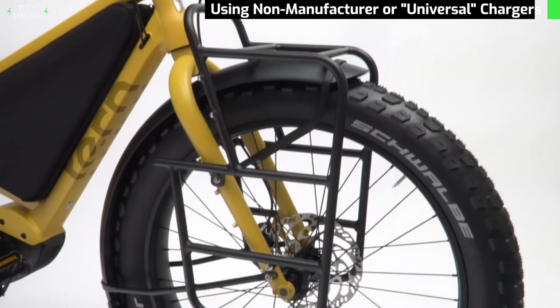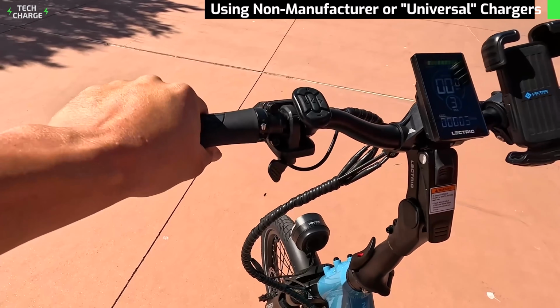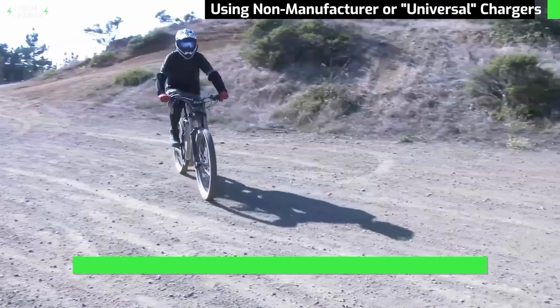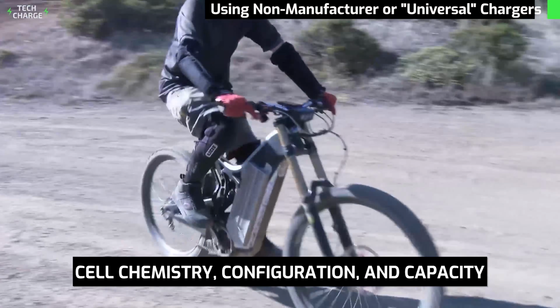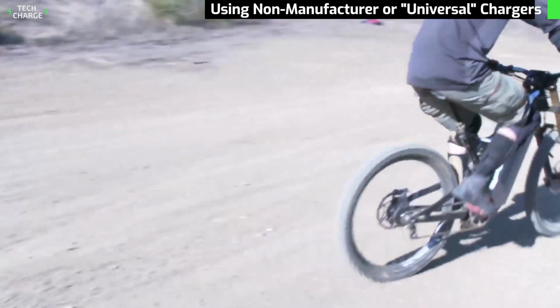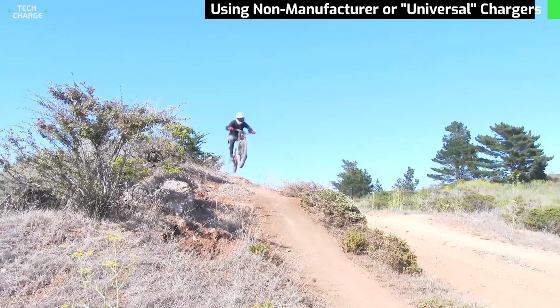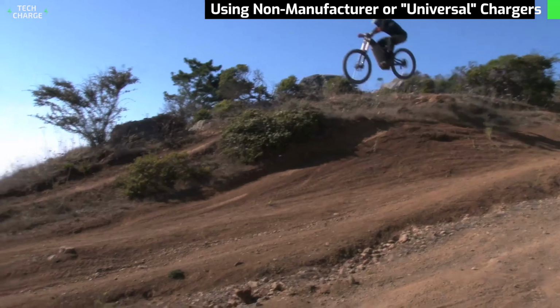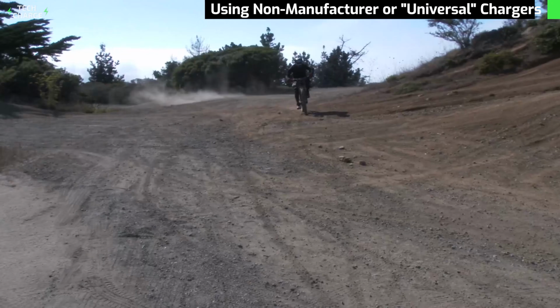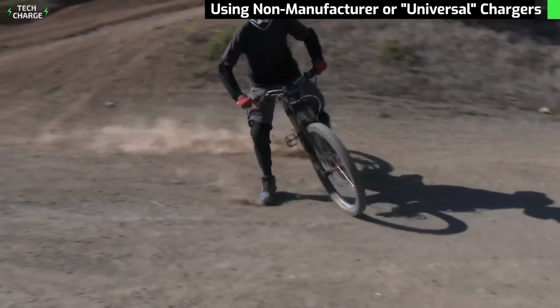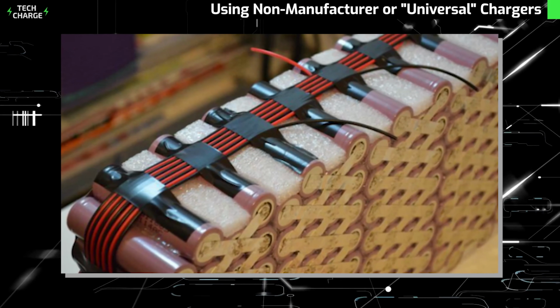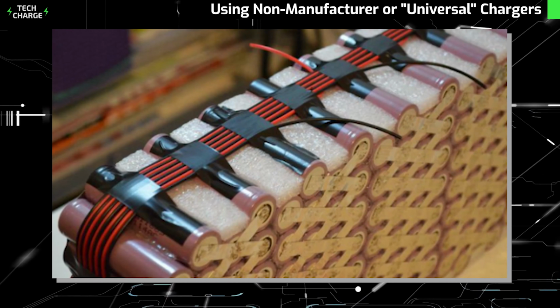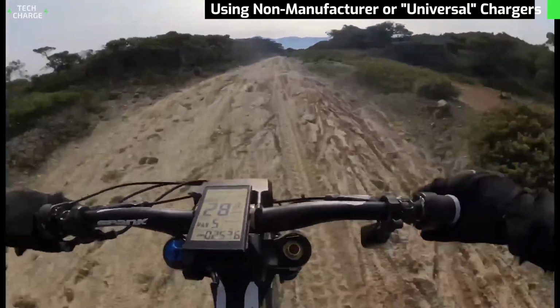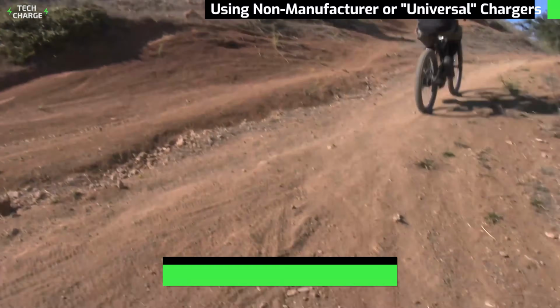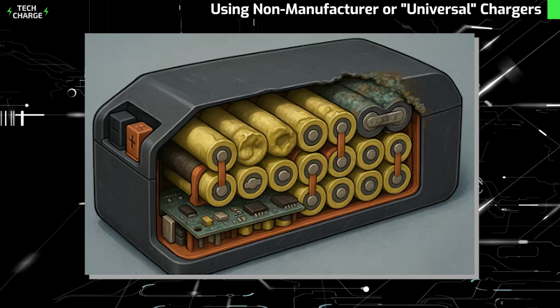The electrical requirements for lithium-ion batteries are extremely specific. Each battery pack has a designed charge profile based on its cell chemistry, configuration, and capacity. An incompatible charger supplies the wrong voltage, wrong current, or both. This electrical mismatch causes multiple problems inside the battery pack. Wrong voltage leads to overcharging, where cells exceed their maximum safe voltage threshold. This forces too many lithium ions into the anode structure, creating mechanical stress that can rupture the electrode material.